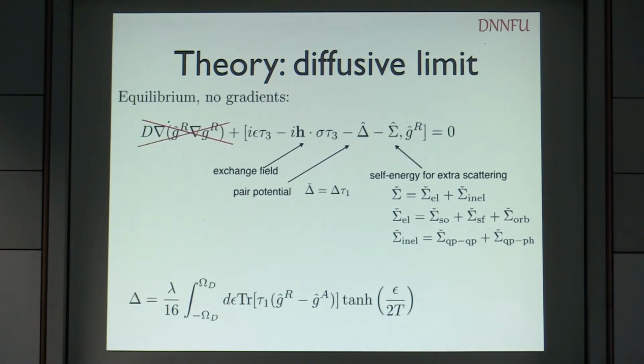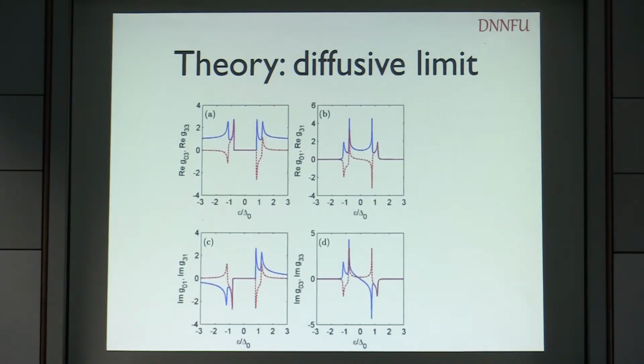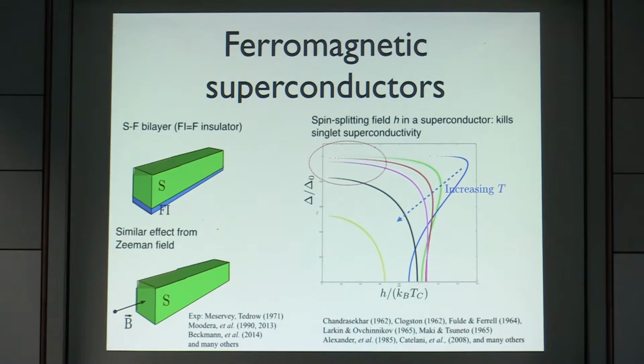Now, the first task was to study what happens to the superconductor next to this ferromagnetic insulator. Let's assume first that it's a bulk superconductor, so we can forget about all gradients and just include this exchange field term and the spin relaxation terms. Then we study this self-consistency equation in equilibrium. In general, you have to solve it numerically, and then you plug it into the self-consistency equation and solve for delta. These are different parts of the Green's function that you get in the process as a function of energy, but it doesn't matter too much.